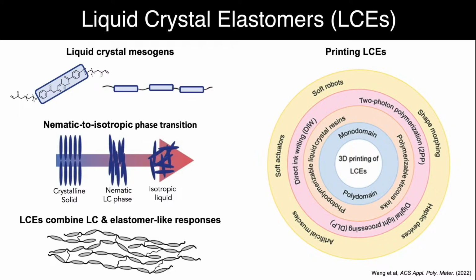A liquid crystal elastomer is essentially a combination of mesogens that are liquid crystal-like, so they have these rigid backbones. In pure liquid crystal form, they undergo transitions as we increase temperature. They go from a highly ordered crystalline-like arrangement to a nematic liquid crystalline phase to an isotropic liquid. As you get more thermal energy, these mesogens eventually become randomly aligned. But there's been a huge resurgence in this field of liquid crystal elastomers, and one can put these rigid mesogens along the backbone of an elastomer-like architecture that's lightly cross-linked, or have them as side chains or end-on configurations. So there are multiple ways to introduce these mesogens.